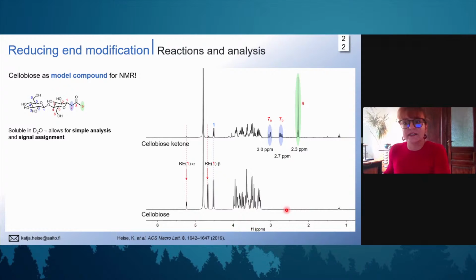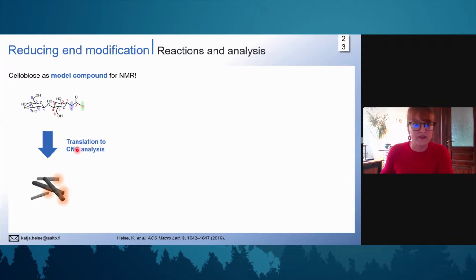So what you see here on the right side, the bottom spectrum, is the standard proton spectrum of cellobiose. And you can also identify the different anomers of the sugars, so the alpha anomer and the beta anomer. And on top, you have the cellobiose ketone. And then you can immediately identify your methylene group signals and also the new signal introduced for the methyl group of the ketone functionality.